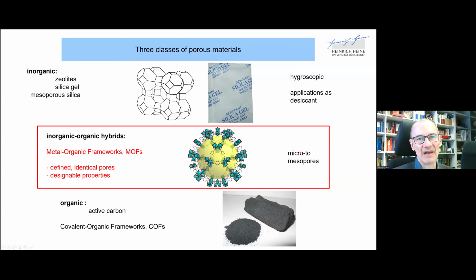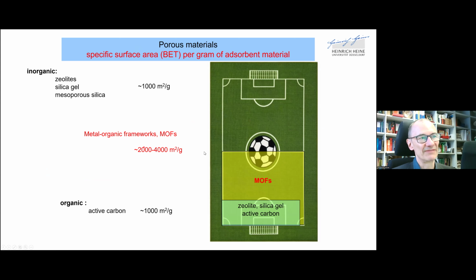So MOFs are largely micro and to some extent mesoporous materials. And in this way, they resemble the zeolites, which are also crystalline and microporous, but zeolites are only to a very limited extent designable in their surface structure and properties. So what is perhaps also important is this range of porosity and surface area. For MOFs, you can say they lie between 2,000 to 4,000 square meters per gram. And this is not even the record value here. There are MOFs which have much higher surface area. And the inorganic class of materials and the organic ones are only about 1,000 square meters per gram.